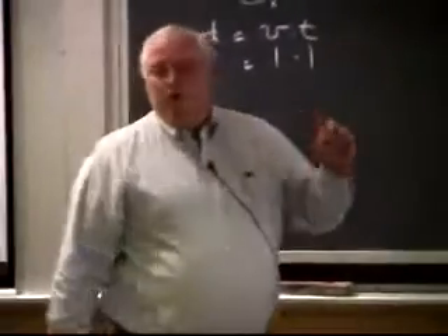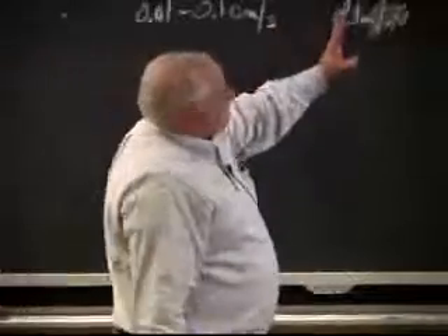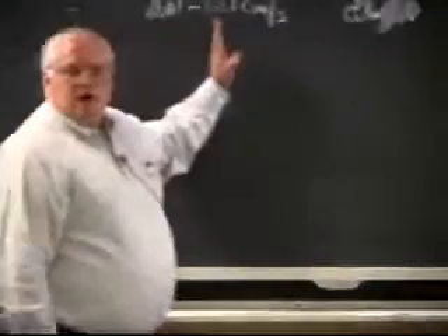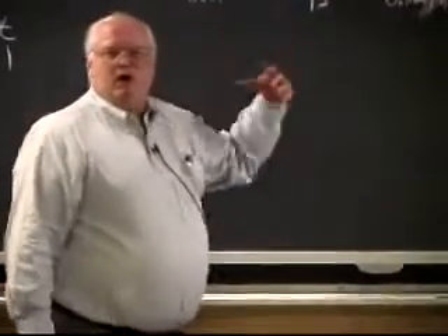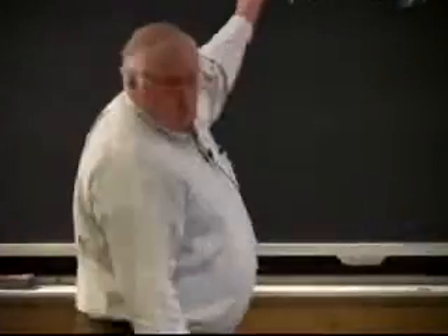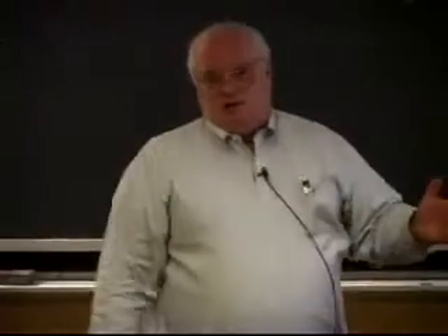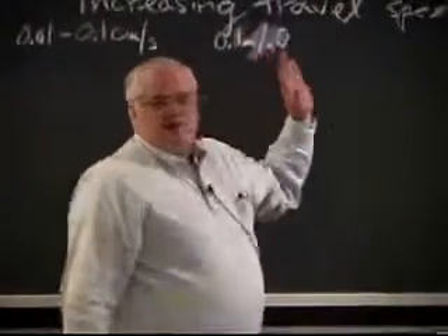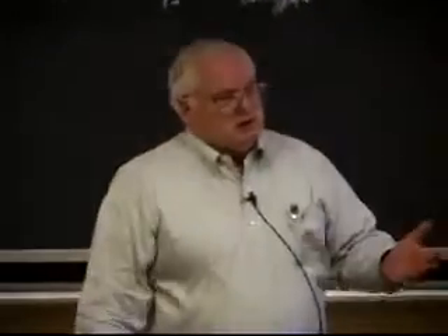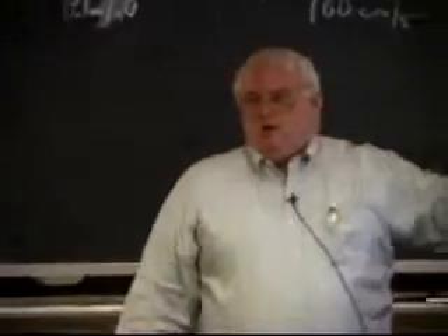But there is actually a point to this. If I'm doing something over here, it turns out the reaction time to control an oxyacetylene weld pool at 1,000 watts per square centimeter is several seconds. And the time to control an arc weld pool is something on the order of a few tens of milliseconds. The time to control a laser or electron beam weld pool is certainly less than a tenth of a second. Probably a few tens of milliseconds. In fact, I know it's a few tens of milliseconds, but for other reasons. It has to do with the inertia of the liquid metal and how fast you can push it away, but we'll talk about that later.